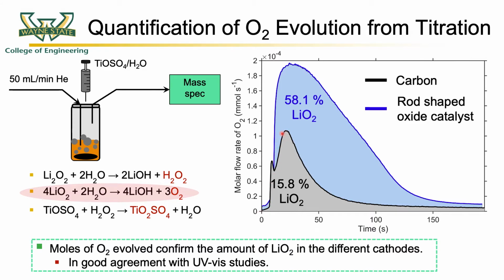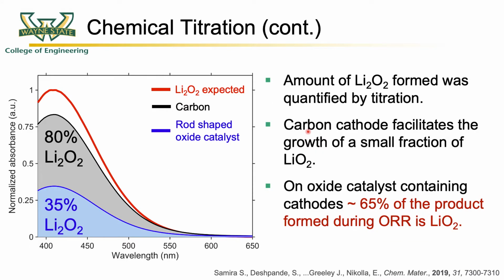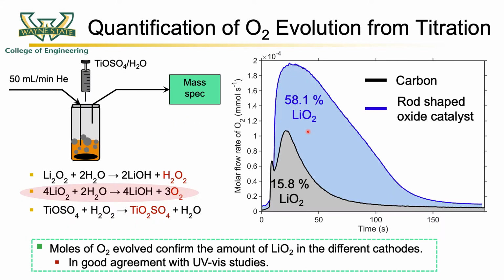On a carbon-only electrode, roughly 16% of the discharged products can be attributed to the presence of LiO2, as measured using the amount of oxygen evolved. On the other hand, on a rod-shaped oxide catalyst containing electrode, about 60% of the discharged species is attributed to the formation of LiO2, consistent with our chemical titration studies shown in the previous slide.